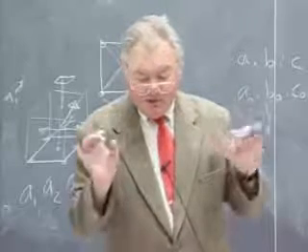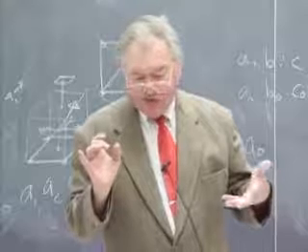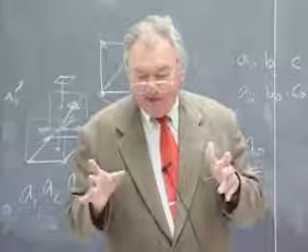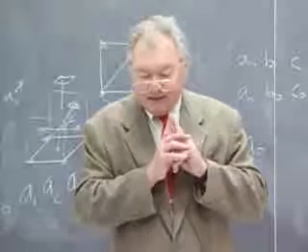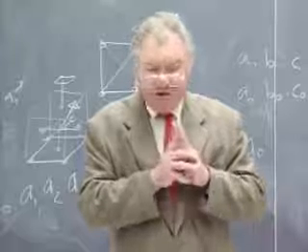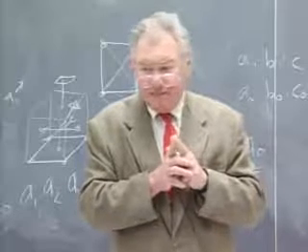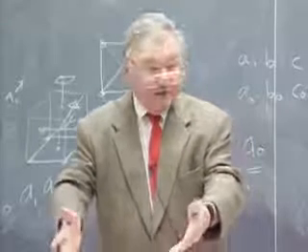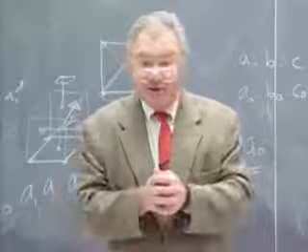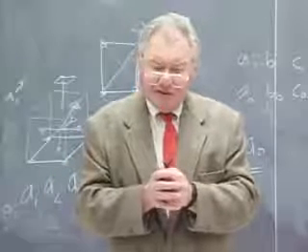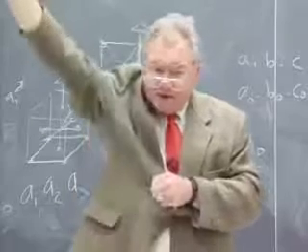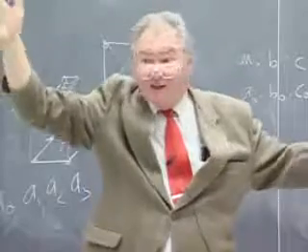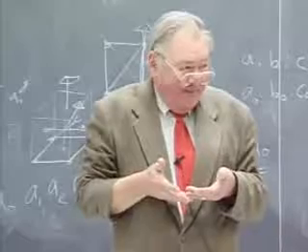Okay, let me in one masterful swoop convince you that we have done almost the better part of the work. Let us ask, what does inversion require of a lattice? What does the symmetry of inversion, which didn't appear in any of the plane groups at all because that's inherently a 3-dimensional point group operation, require? Well, think about it. All inversion says is that if there's a translation t that goes up this way, there should be another translation minus t in the opposite direction. And any lattice whatsoever can make that claim and satisfy that requirement.